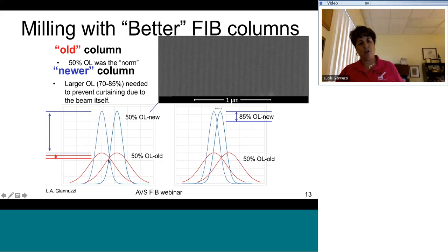But in some of the newer columns, what I've noticed is that with a 50% overlap, because the beam density is much higher, the beam is actually better. But then the distance between the hot spot of the beam and the beam tails is much greater. And if you look at the cross-section, you actually get these curtaining artifacts just due to the beam effect itself. Okay? And these curtaining artifacts will appear on your sample surface, which is not particularly good. The way to get around that is you can do one of two things. One, you can defocus the beam to spread it out so that you get something more like this. Or the other thing you can do is go to 85% overlap, for example, such that the relationship between the hot spot of the beam and the beam tails is about the same as it was on an older beam.